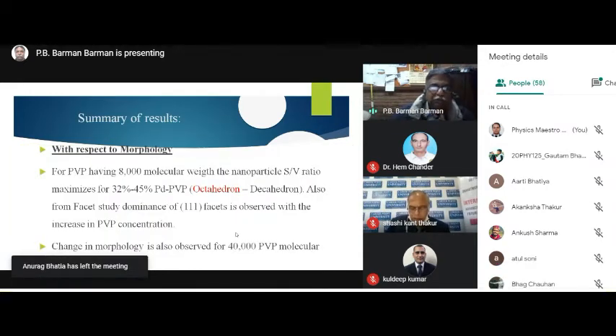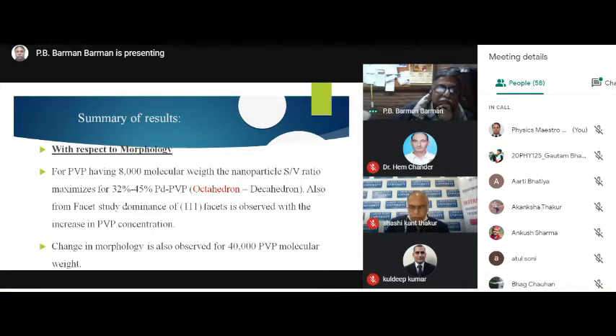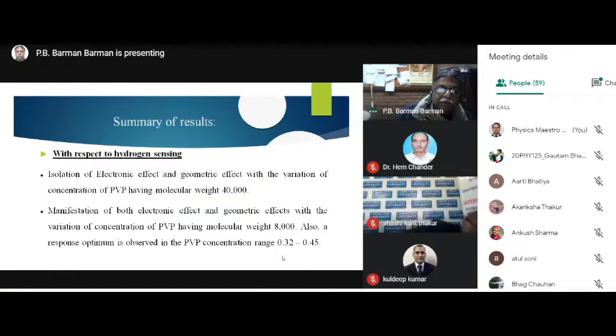Finally, with respect to morphology, for PVP having 8,000 molecular weight, the nanoparticle surface to volume ratio maximizes for 32 to 45%, but definitely 32% is better, that is octahedron versus decahedron. Also from facet study, the dominance of the 111 facet is observed with increase in PVP concentration, and the change in morphology is also observed from 40,000 PVP molecular weight.